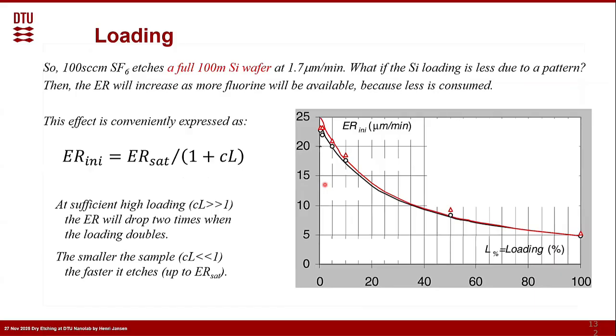What should we do now? Well, we know that we calculated here for the 100 millimeter, that is this area. But if we now have a silicon loading of, let's say, 50%, then our area is, instead of the 100 millimeter wafer, half of it. Sorry, it's not 50 millimeter diameter then, but it's half of the area. That means, of course, that the etch rate will be doubled, because we are going to etch the same amount of material. I think it's a formula of Mogab, who first came up with this.